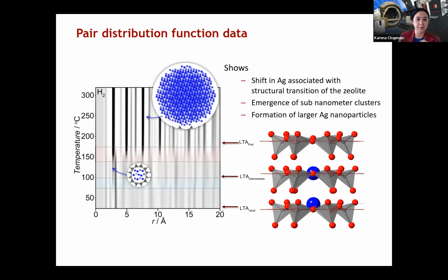Just to orient you, if we look at the PDF, what we actually see is we have our silvers sitting in the 6 ring. We see the silver move into the center of the 6 ring in some kind of intermediate state. Eventually, the silver forms small clusters that are confined by the zeolite. These are about maybe 8 angstrom clusters. And eventually they grow to large nanoparticles, which must be sitting on the surface of the zeolite.